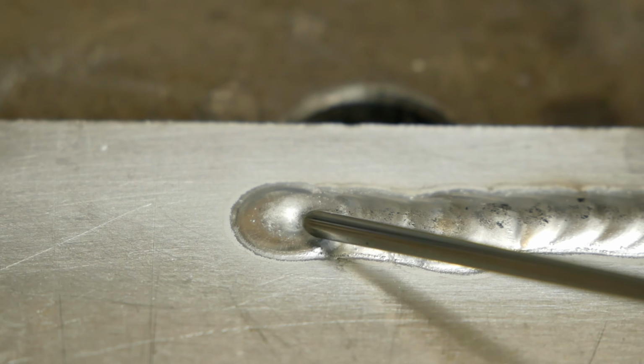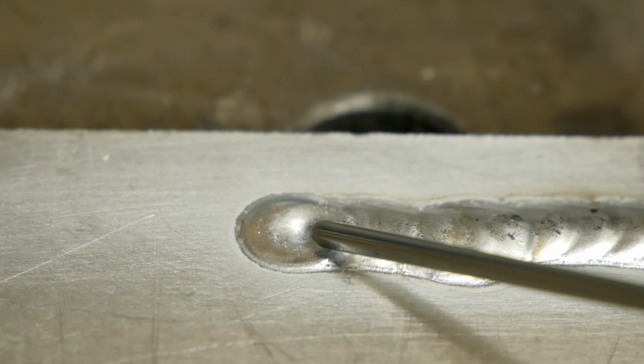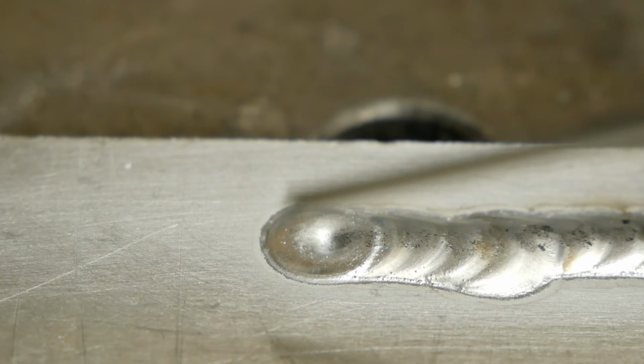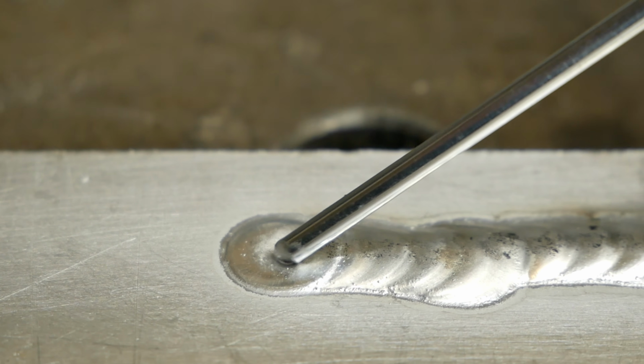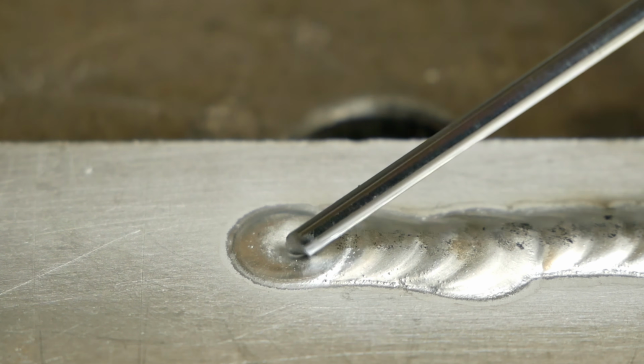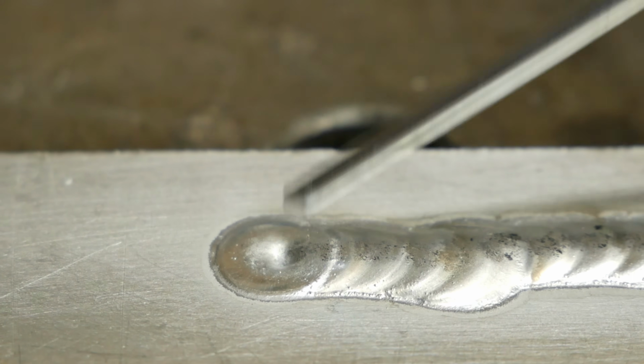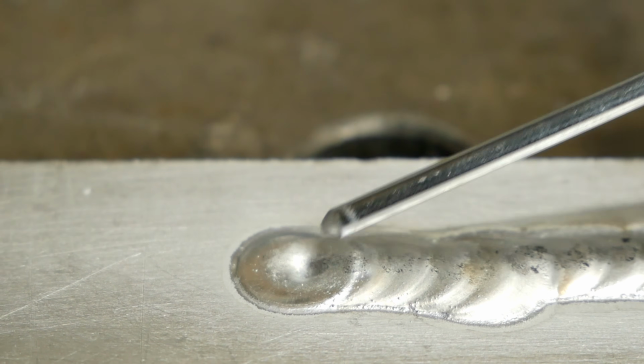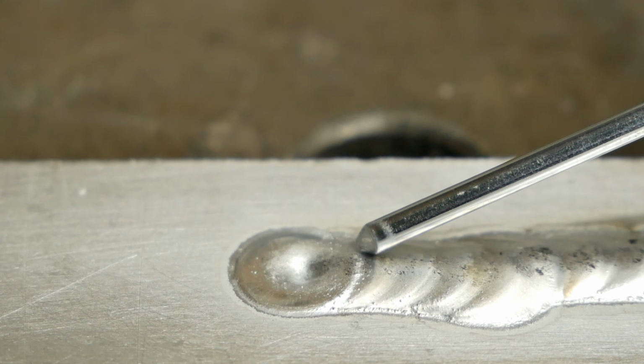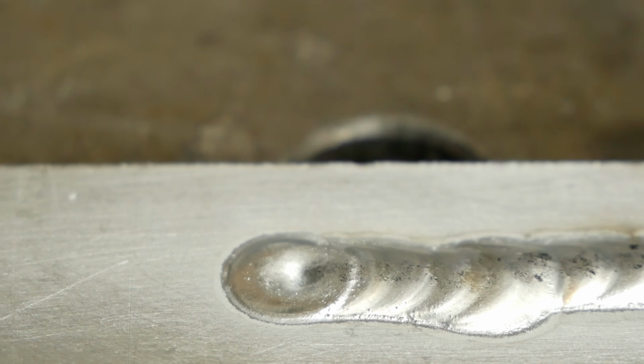If you don't ramp down your amps and add filler at the end, you'll get a crater. So here's what happens if you just drop your amps off really quickly without adding any filler. You'll get this actual crater right in here, which is prone to stress cracking. So you definitely want to add a little filler right at the very end and ramp your amps down, and even bring your arc back here a little bit as you drop it completely off.